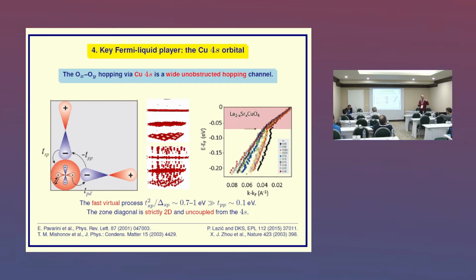So that's a very big effective hopping, which is much bigger than the direct chemical t_pp, which is only 0.1 electron volt. And this observation is enough to understand why, when you fit ARPES in a 3-band model, you always need to put an artificially large t_pp, because this conflates with the 4s process. So we have a fast virtual process which completely avoids this correlated mess in the d orbital. And now there is a very interesting symmetry of this model, highly significant for the cuprates. It's almost like a conspiracy.